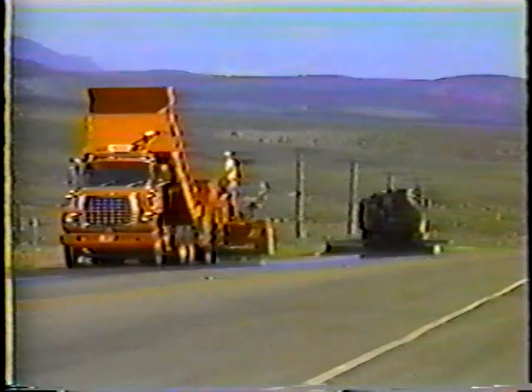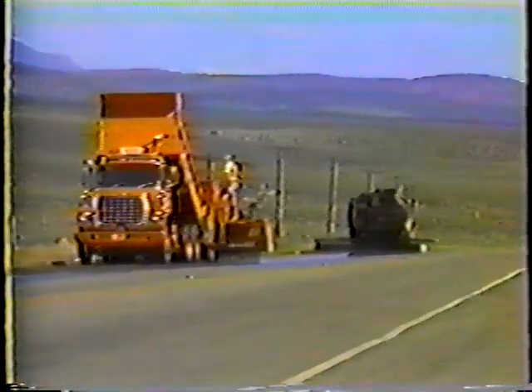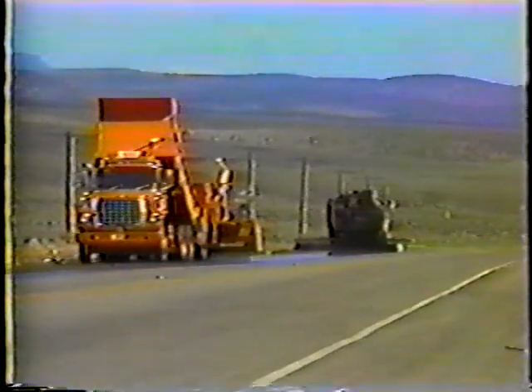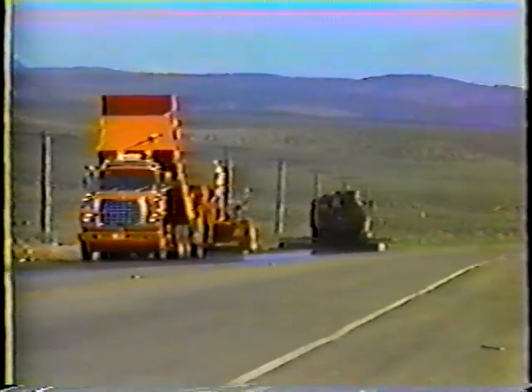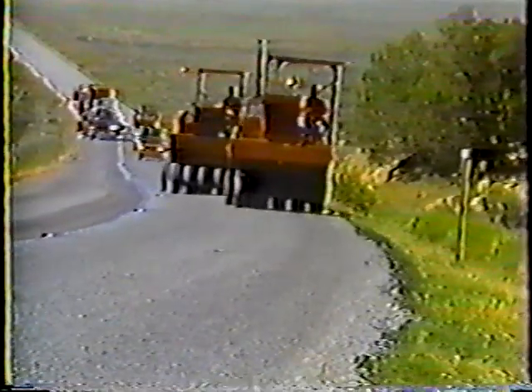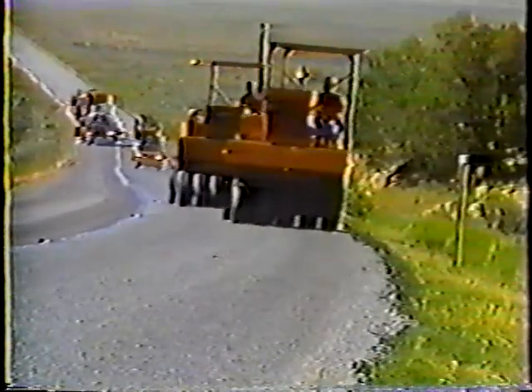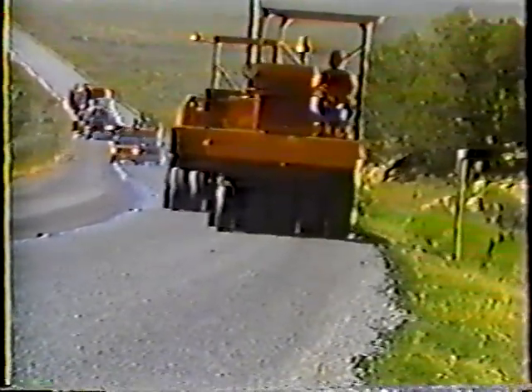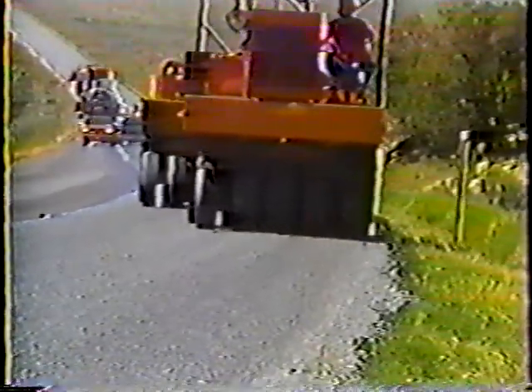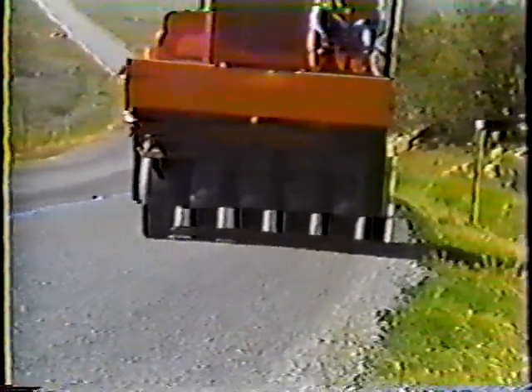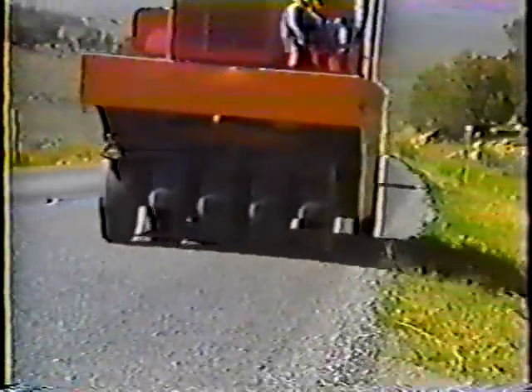The application of the cover material, like the liquid asphalt, has to be uniform. Again, about 3/4 of each stone should be embedded in the liquid asphalt. But beyond that, the stones have to be placed close together so that only a small amount of liquid asphalt shows through. But the chip spreader can't do it all. That's why there's one more step. Rollers follow closely behind the spreader to make sure that all the material is firmly seated in the liquid asphalt and that the stones are lying flat, not one on top of another.